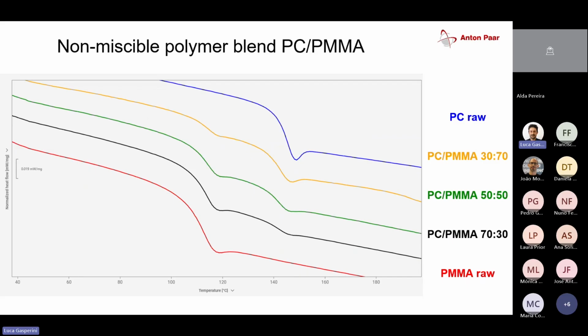This is something that you've seen before from Matthias and Florian as well. This is the polymer blend of PC-PMMA, and this is the perspective that the DSC offers us. So again, we have a glass transition from the raw polycarbonate and the glass transition from the raw PMMA, and then the 3 blends with different ratios, 30-70 through 50-50 up to 70-30. And this is the outcome. What we see is one glass transition, of course, for the individual components, PC and PMMA. When we took the samples, the PMMA was transparent, while the polycarbonate and all the 3 mixtures were white in color, so they looked exactly the same.